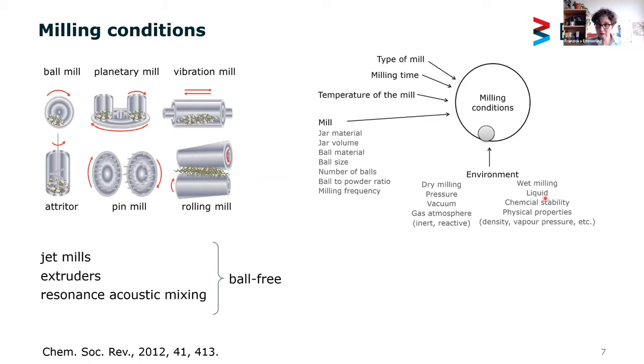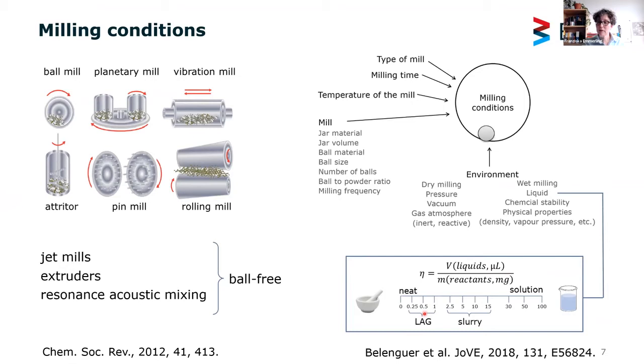As you might know from the literature, this eta value was created to differentiate between neat grinding on the one side, where we have really no solvent present, and then moving on to liquid-assisted grinding, where we have small catalytic amounts of solvents, and then we move on to slurries, and then we are really in solution.